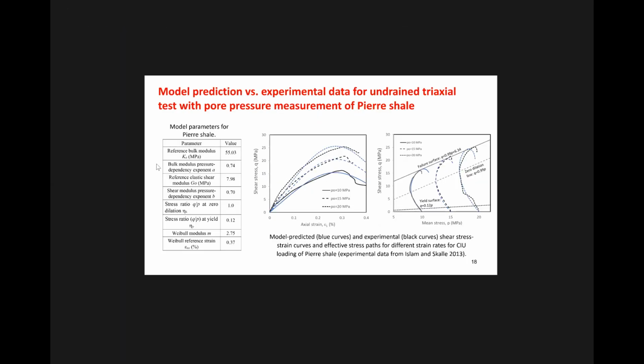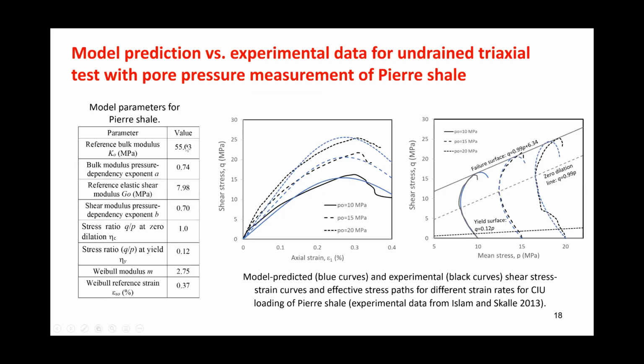So here's a comparison. We now have more parameters, 8 parameters, I believe: 1, 2, 3, 4, 5, 6, 7, 8 parameters that are needed. So this is compared with the results on Pierre shale by Islam and Skalle. Okay, these results were taken. Note that there are very few undrained triaxial shear tests on shale with pore pressure measurements. It's very difficult. It takes a long time for the pore pressure to equilibrate in the sample. Okay, so these are very good results.